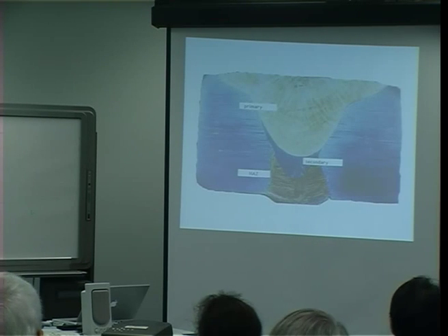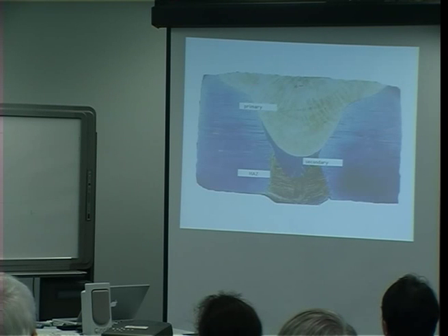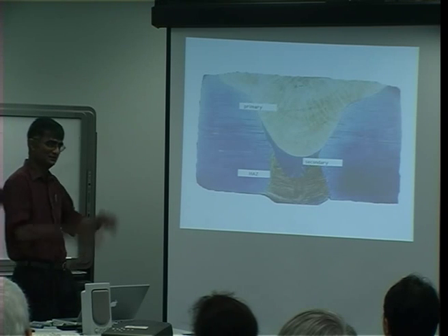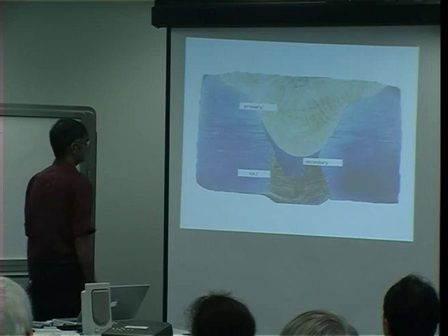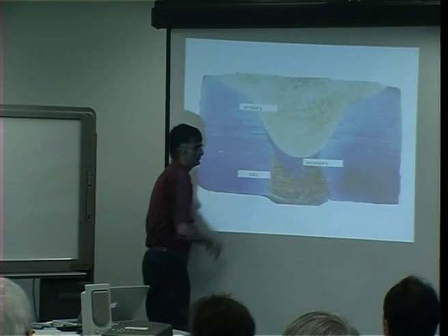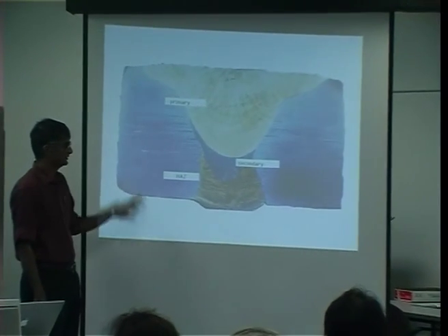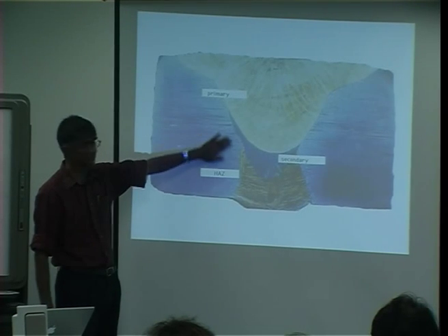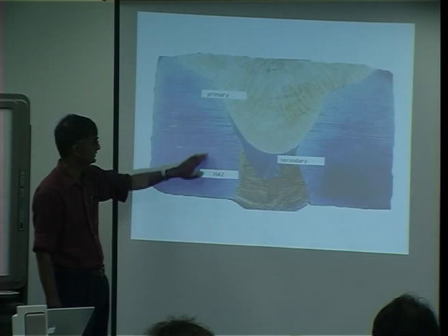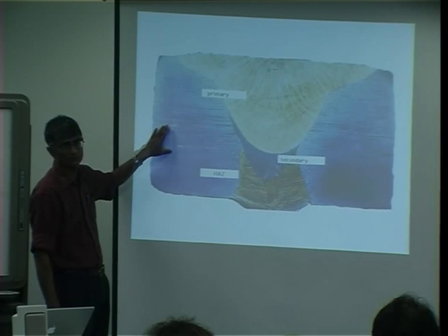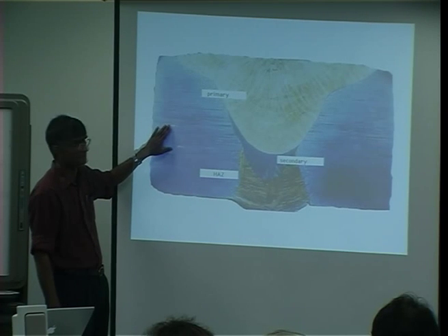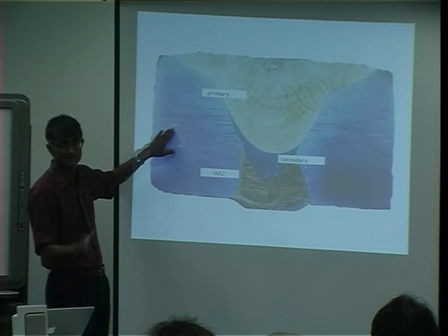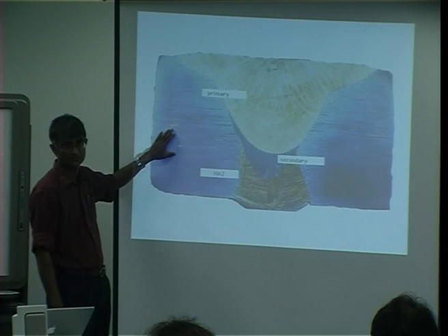And this is a very simple weld metal, compared with the sort of things that Wotec and John are doing, which have about 30 different passes and really deep welds and so forth. Here we have just three layers deposited on top of each other, and the color etching reveals that all of them have a different microstructure, and indeed we've got a change in the heat affected zone, and the parent plate far away from the weld also has contrast indicating chemical segregation in the plate.